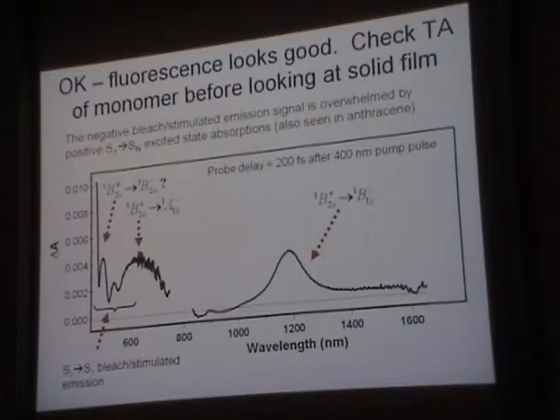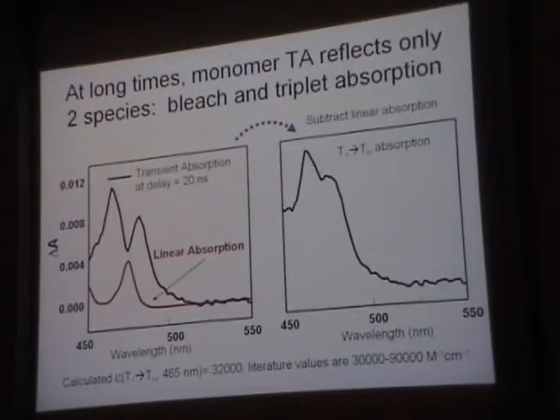The other thing I would say, a lot of people in solid state spectroscopy identify features in the near IR and say this is a charge transfer exciton, or this is the triplet, or this is something else. But it should be said that that feature is there when you excite the monomer to the singlet state. Right? So you have to be a little careful about assigning near-infrared transitions. Just because they're there in the solid doesn't mean that they're not also there in the single molecule in the liquid. And that's what we see in tetracene. This has also sort of been seen in anthracene, although these spectroscopies haven't been very well done.